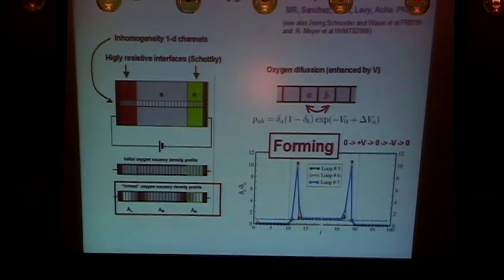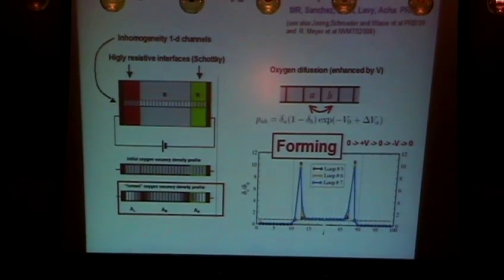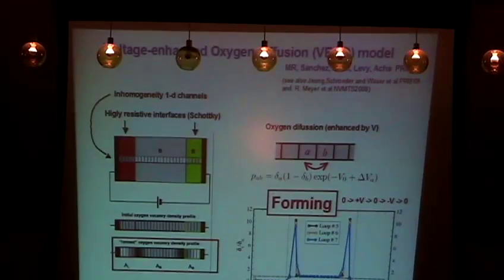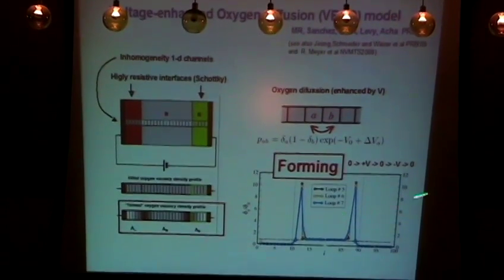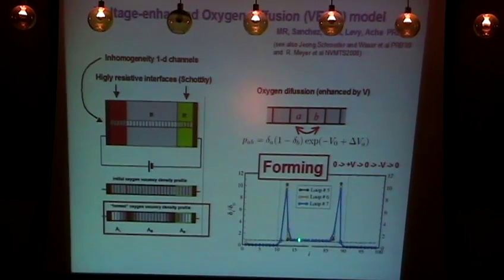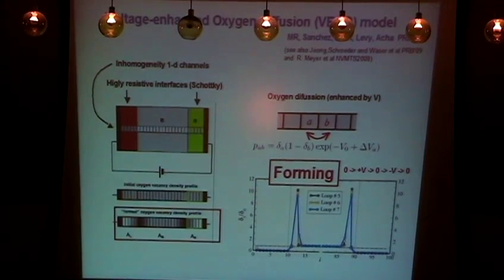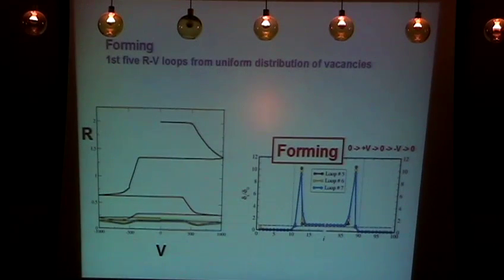The forming is just having the system run up and down for several loops, and this is what you get after the first few loops. In order to get more detail, this is what happens with the forming. You start with the resistance of the system, which is homogeneous, and then you ramp it for 5 loops. So this is the first loop, you get a change of the resistance. Second loop, you get that. Third loop, you get that.